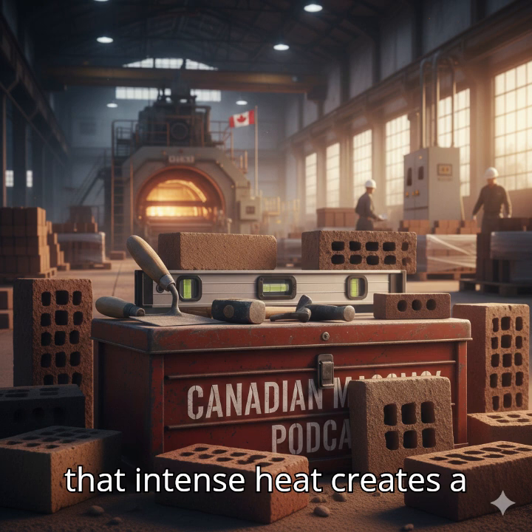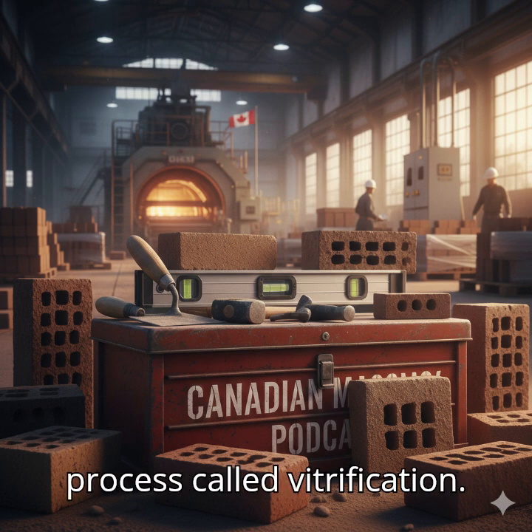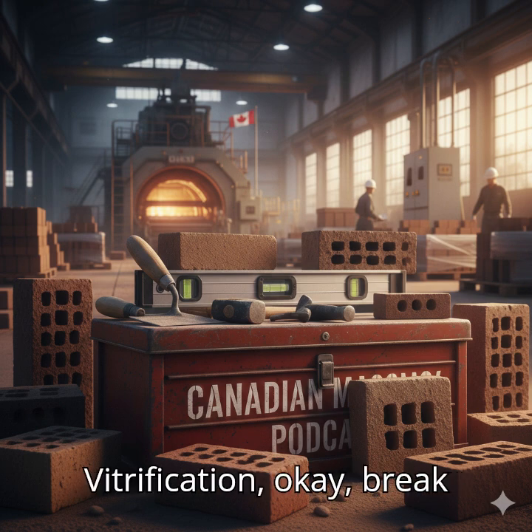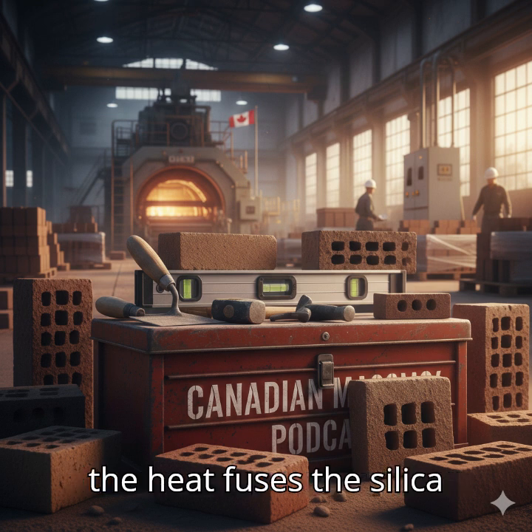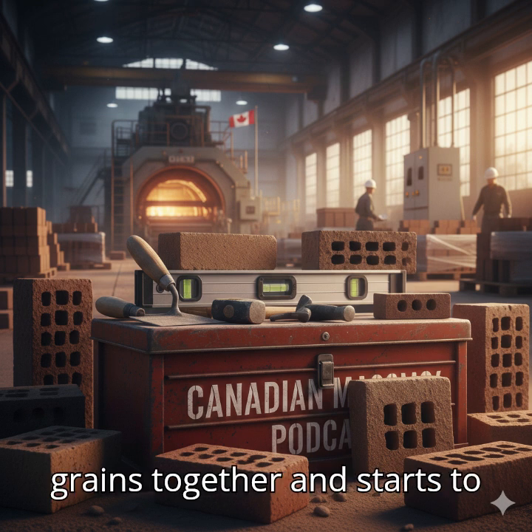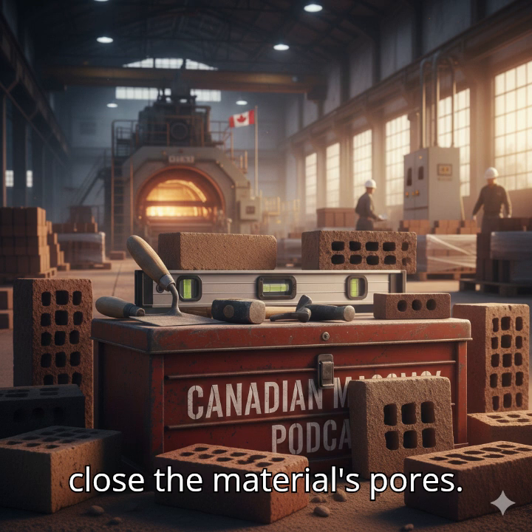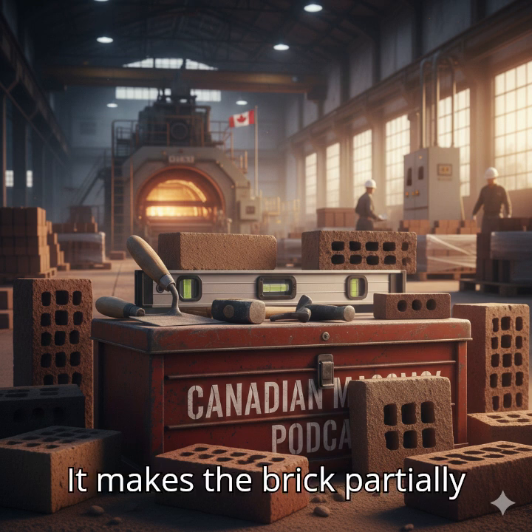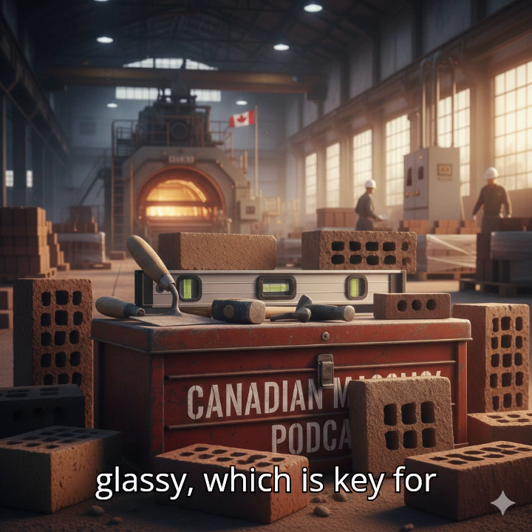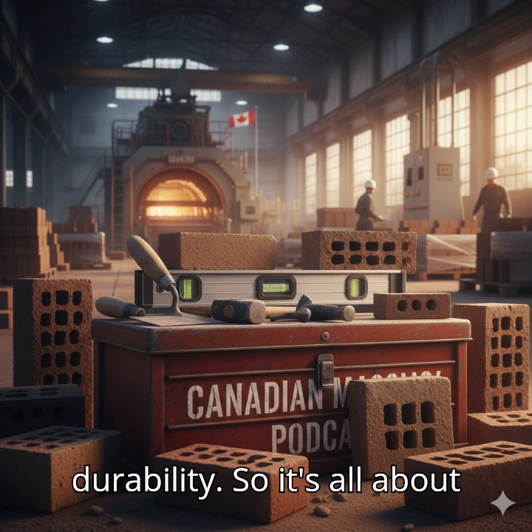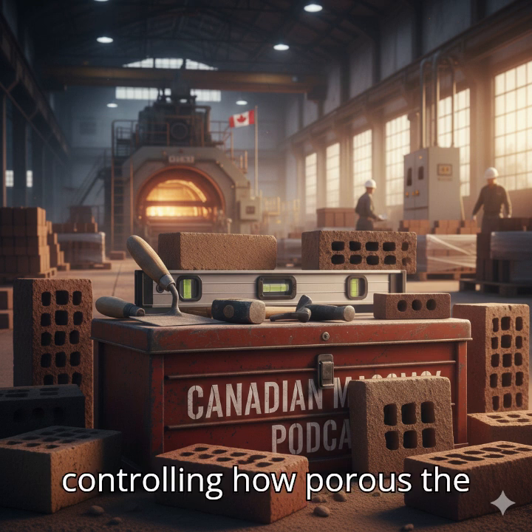But that intense heat creates a process called vitrification. Okay, break that down for us. It's when the heat fuses the silica grains together and starts to close the material's pores. It makes the brick partially glassy, which is key for durability. So it's all about controlling how porous the brick is.